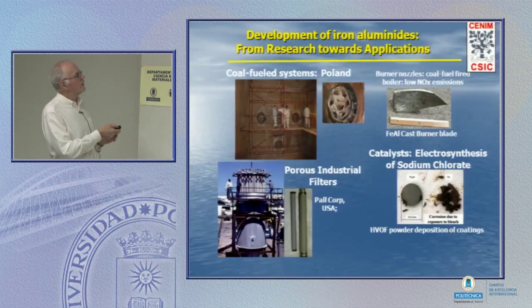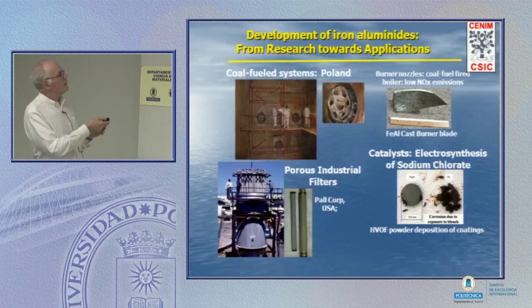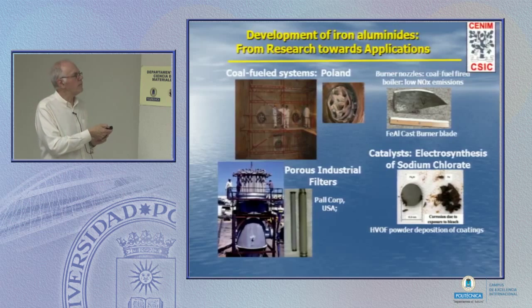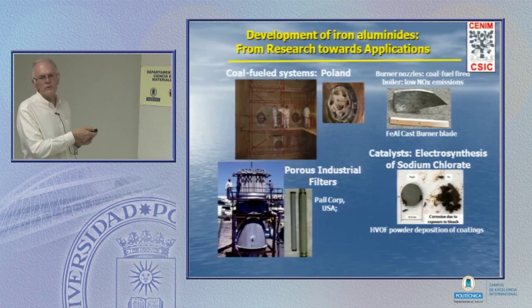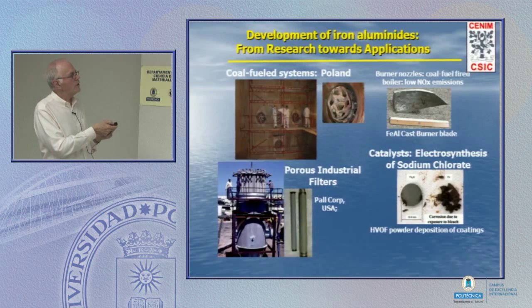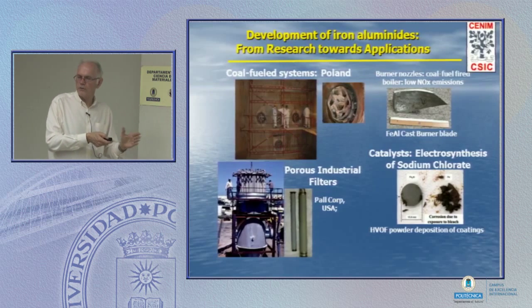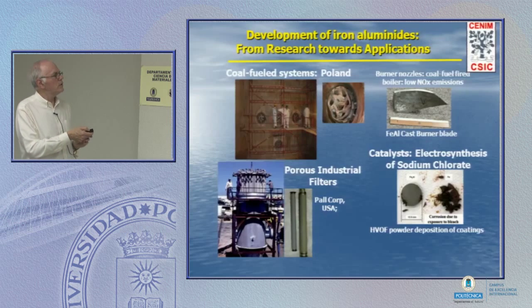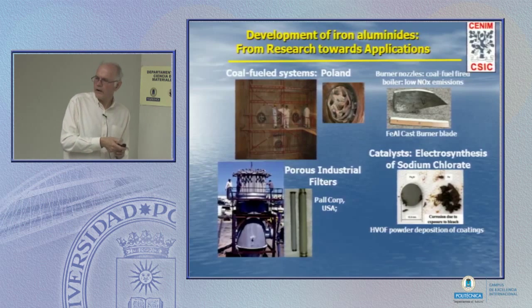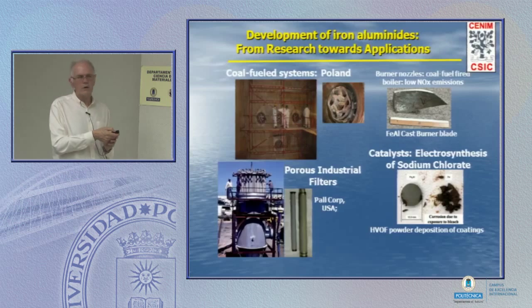So where are we in terms of applications? The picture's a little bit dark here. This is the burner of this coal dust burning power plant in Poland. Here are a couple of humans giving you some idea of the scale. This is the nozzle where the coal dust and maybe air or oxygen is injected. Here's a burner, and inside the burner we've got these blades that are controlling the flow and the direction of flow of the coal dust and the oxygen. And when these were made of high chromium, high nickel refractory steels, their lifetime was very short indeed. Made of iron aluminide, there's absolutely no problem.